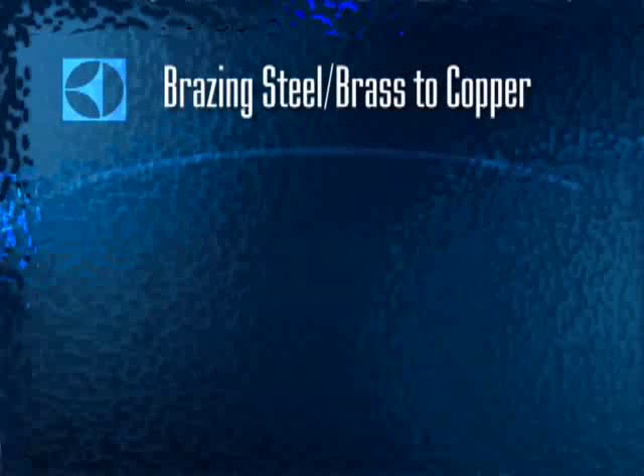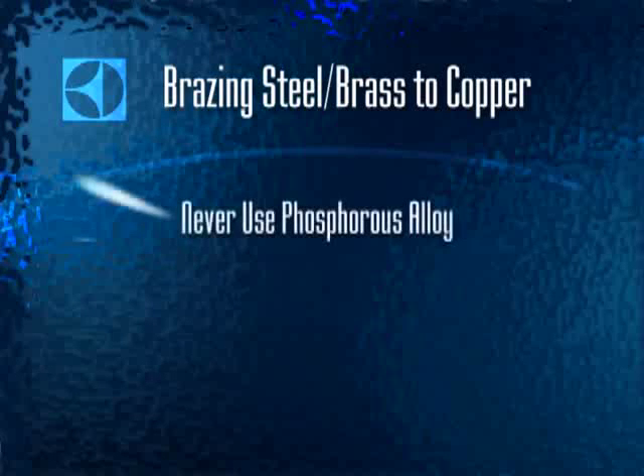When brazing steel or brass, or brazing these metals to copper, you must use the appropriate filler metal for those base metals. Never use a phosphorus-bearing alloy to braze steel. The joint will be brittle. Also, take care when brazing copper-coated steel. If in doubt, use a silver brazing alloy.